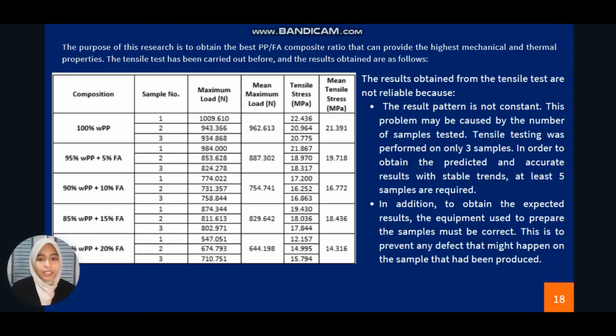So the second factor is that the equipment used to prepare the sample is not proper, because during the preparation of the sample, we only used a handsaw to cut the composite into the dog bone shape. So it is not accurate. Actually, we need to use the cutting machine that is provided in the lab, in the workshop, to get an accurate dog bone shape. So it will not cause any defect or inaccurate result for the testing.